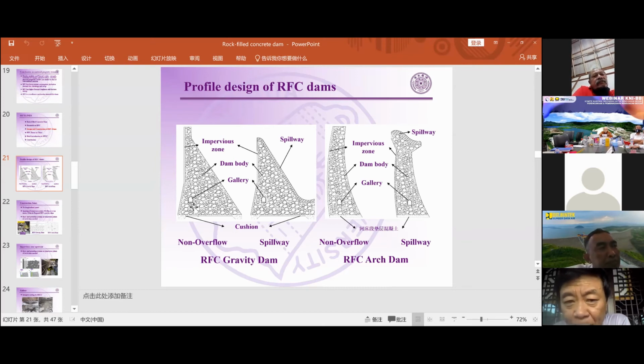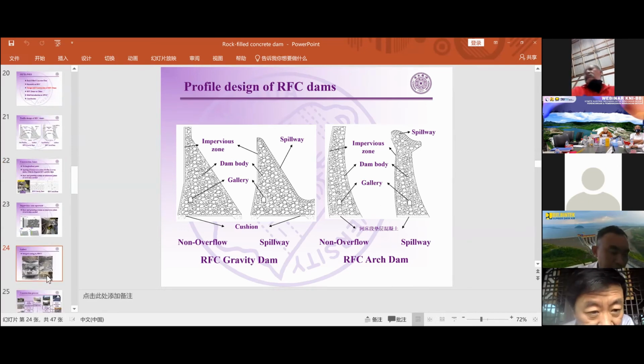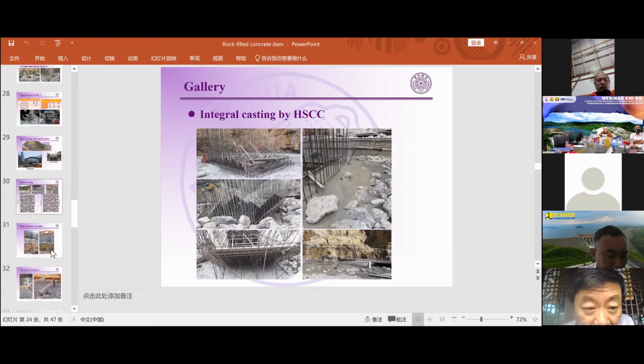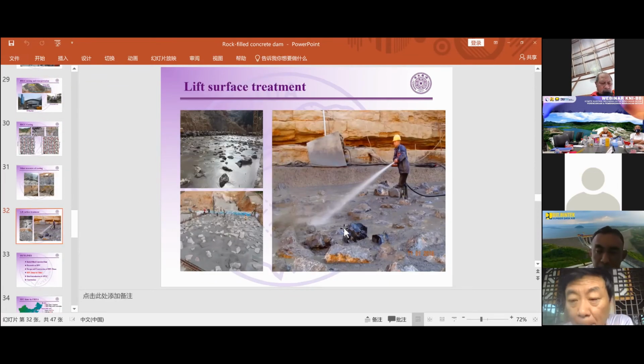Why do we set the impervious zone for the conservation? Because there was some worry about the seepage, not along the rock-filled concrete itself. We worry about the lift surface, the lift surface between the two lifts. We have to use the green cutting. We have used green cutting, and after green cutting you can get a very clean surface of the lift.